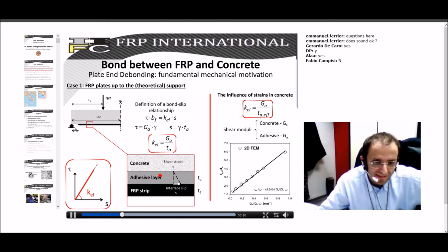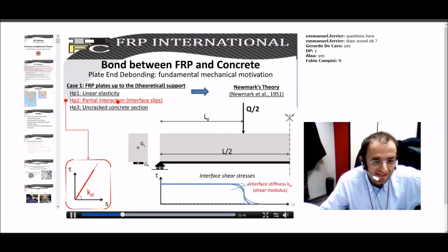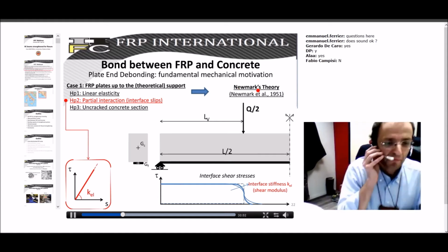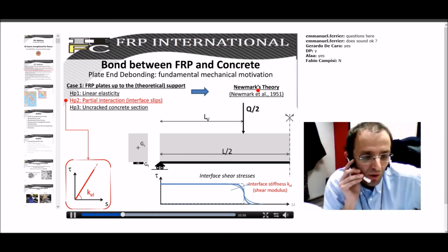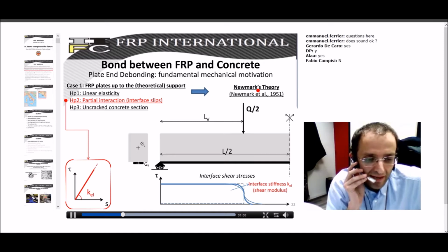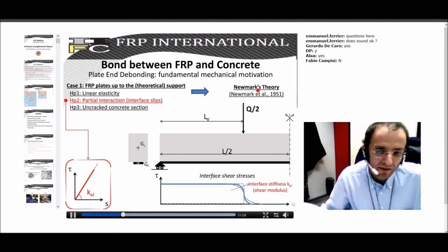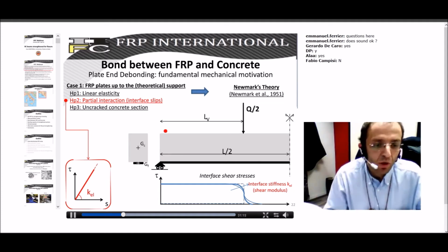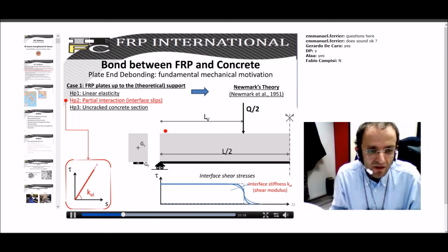What is important is that there is a flexible layer between our FRP and our concrete, which means that plane sections cannot remain plane. When you have this kind of kinematics, you are in partial interaction because there is this adhesive layer, and for this situation you have the Newmark theory, which maybe is not so common as the Jourawski one, but those of you who are familiar with two-layer composite sections, especially with steel-concrete composite systems, are probably familiar with the Newmark theory, which is not complicated, but it is based on some differential equations, which here, for the sake of simplicity, are omitted.